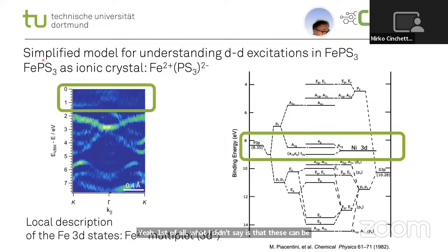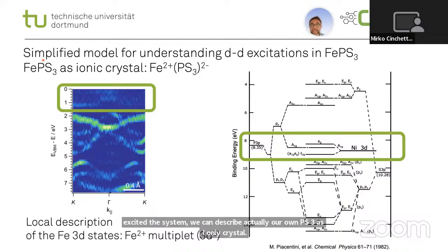But we can actually also use a simplified model to understand the excitation of this material when we use photon energies that are more or less in the range of the band gap. So in order to understand what happens when we optically excite the system, we can describe iron PS3 as an ionic crystal. So we have iron 2+ and then PS3 2-.